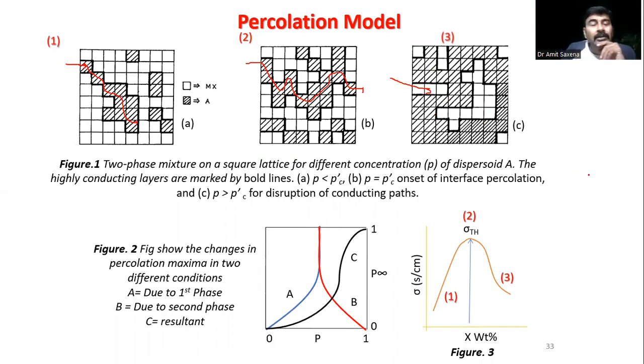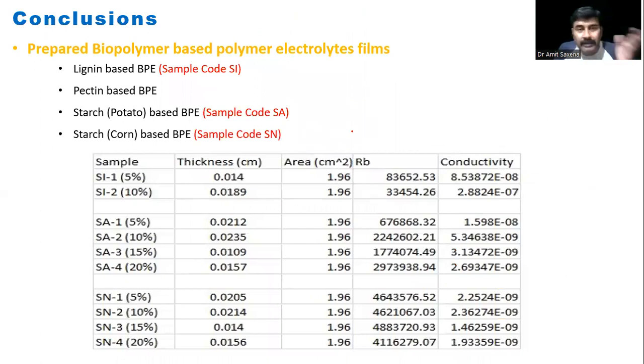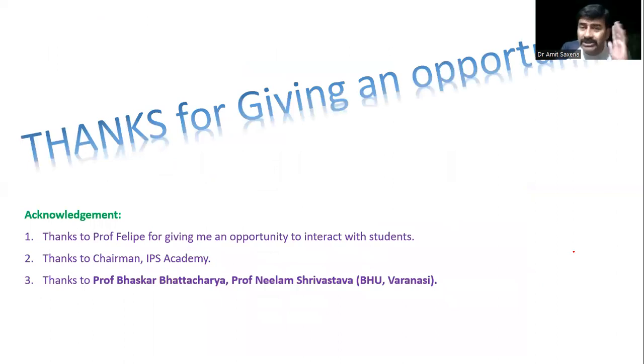So finally, what I conclude is that we prepared biopolymer-based polymer electrolytes, and these polymer electrolytes offer a good level of conductivity. They can be used as a sandwich between two electrodes, and we can synthesize batteries out of this. In our case, we use different samples, different thicknesses and conductivities. As I mentioned, the highest conductivity was around 10^-7. In the recent past, it is close to 10^-5 and 10^-6. This shows that biopolymers still have good space to work on, to think about how we can increase the ionic conductivity. So this is all from my side.